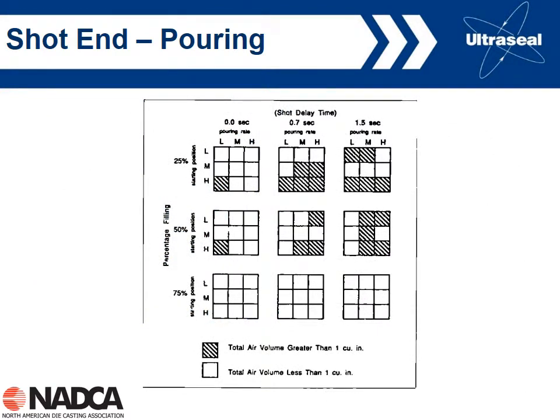So let's talk about pouring in terms of the delay time. What we're looking at here again is experimental data. Up here we're looking at percentage fill of 25, 50, 75%. Across the top we're looking at shot delay time: 0 delay, 0.7 seconds delay, 1.5 seconds delay. Then we've got pouring rate, low, medium, high for each one of these, and then a starting position. So we've got a lot of data shown in this graph.